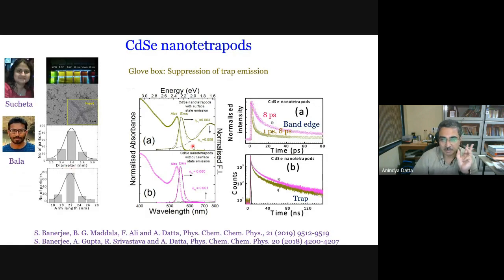So we were able to make two kinds of tetrapods. The one in the bottom, the B panel, showed only bandgap emission, and the one on top was dual emissive, showing bandgap as well as trap emission. And when we looked at the PL dynamics, we found that when we had only bandgap emission, the photoluminescence decayed with a time constant of about 8 picosecond. There are some minor long components as well, but by and large 8 picosecond. When we have the trap and we monitor bandgap emission, we observe an additional 1 picosecond component, which we assigned to the trapping time. And when we looked at the trap emission, the redshifted emission here, the lifetime associated with this emission was pretty long, tens of nanosecond, and as you can see, it is definitely not exponential.